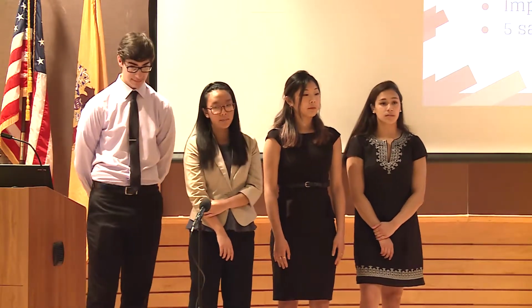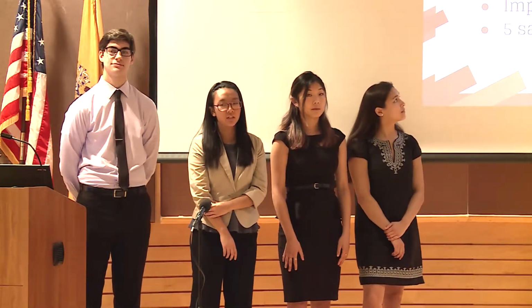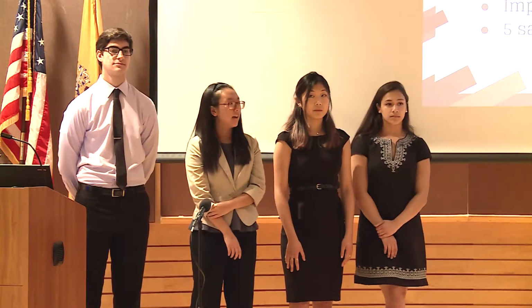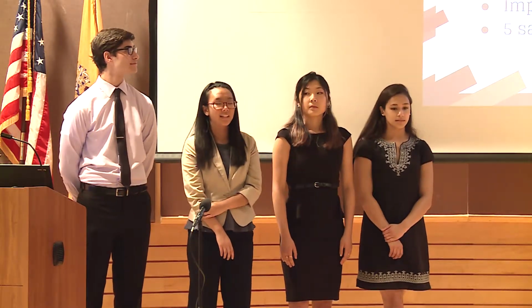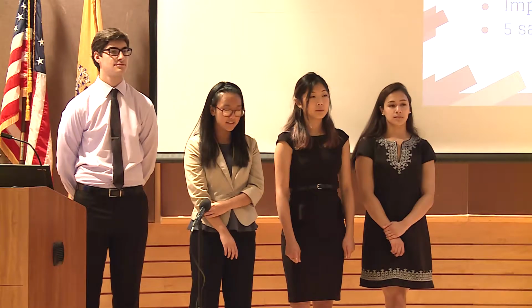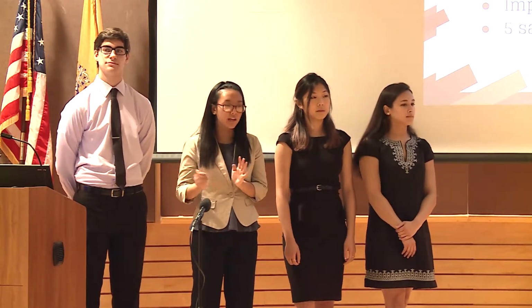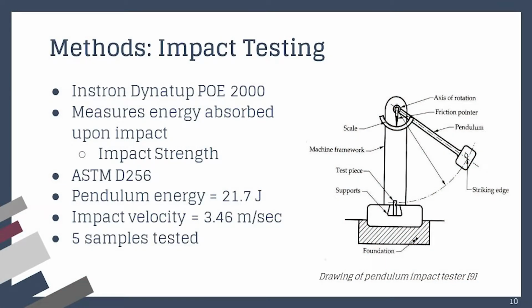So one of the first tests that we completed upon our specimens was impact testing. Impact testing is a destructive mechanical test that's meant to measure how much energy is absorbed once the test specimen is impacted by a swinging pendulum, as seen in the diagram. We used a machine that's called the Instron Dynatup POE 2000, and we followed the American Standard Test Method ASTM D256, and we tested 5 samples.